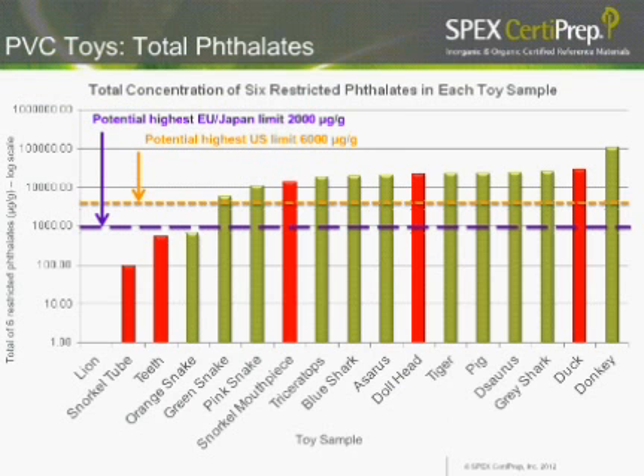If we looked at the total phthalates, you can see the potentially highest values you could get for the phthalates for some of the regulatory methods. Potentially the highest amount of total phthalates you can have in the EU or European method is 0.2, assuming you have 0.1 of the oral contact phthalates and 0.1 of the general restricted phthalates. And for the US, you could potentially go up to 0.6 or 6,000 micrograms per gram total, assuming you are within the limits of 0.1% for each. And as you can obviously see, most of these toys would violate both limits.